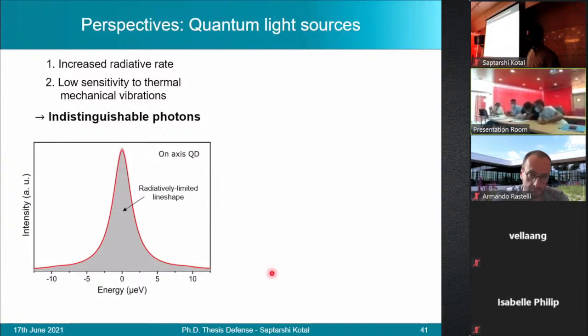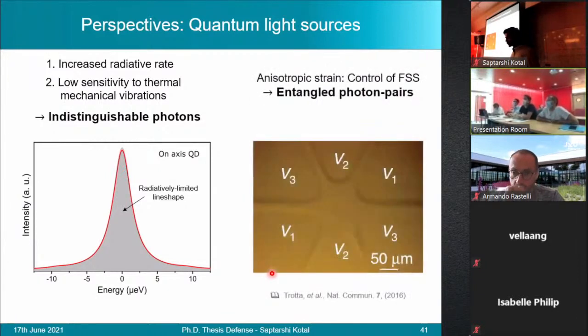Next, thanks to the nanoscale volume of the nanocavities, they are expected to have a low sensitivity to the vibrational modes of the device. Coupled to this, the fact that they also produce increased radiative rate would make them an appealing platform to generate indistinguishable photons. Alternatively, we could consider placing the nanocavities on a structured piezoelectric actuator in order to generate anisotropic strain on the level of the quantum dots, thereby restoring the symmetry of the dot to produce entangled photon pairs.